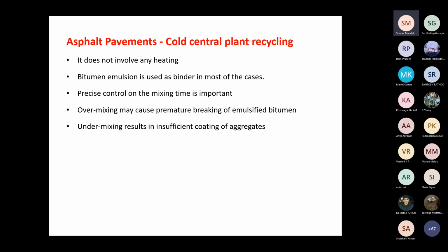This one does not involve any heating, and bitumen emulsion is used instead of bitumen as binder. So precise control of the mixing time is important. Over-mixing may cause premature breaking of the emulsified bitumen, and under-mixing results in insufficient coating of the aggregate.